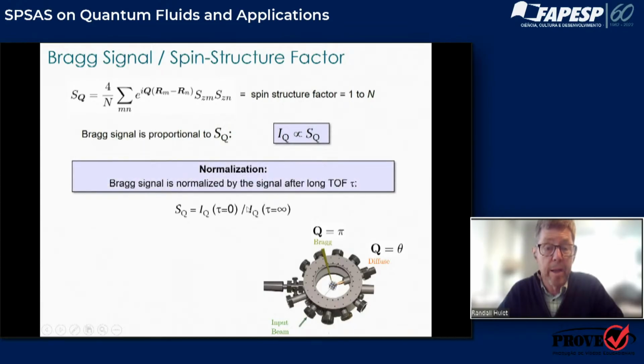And you can normalize it. You don't have to calculate exactly what the transmissions of the windows and all of that are. You can simply normalize by the intensity of light coming out at the particular Bragg angle after long times of flight, after you remove the atoms from the lattice. So that's our normalization. So in fact, this is a proportionality, but these are equalities. So one just needs to make two measurements.